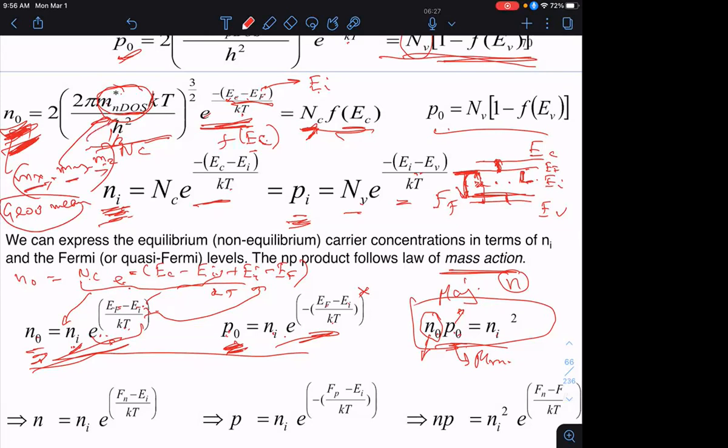Now in the next class, we'll introduce yet a third effective mass. That's called the conductivity effective mass, which is used for calculating currents and all that. And there you can see that you have to use the harmonic mean. So things get pretty hairy. I'll summarize all of this in the next lecture. So for now, you see that you start with the band structures. From the curvature, you get the starting mass, which is the band curvature effective masses.